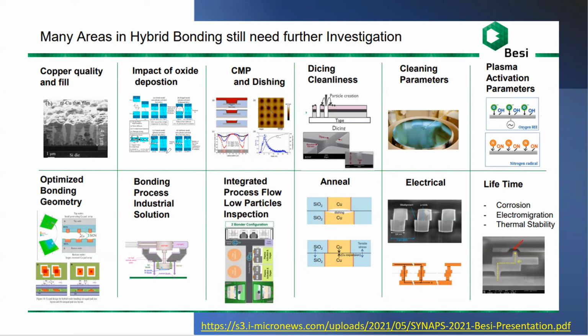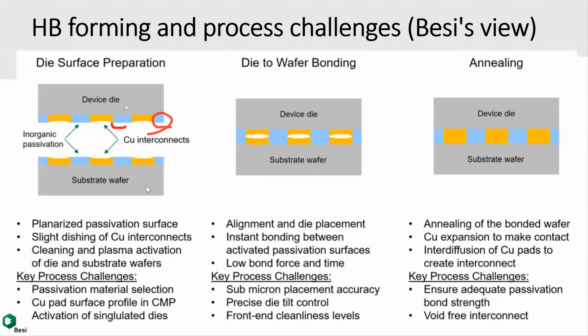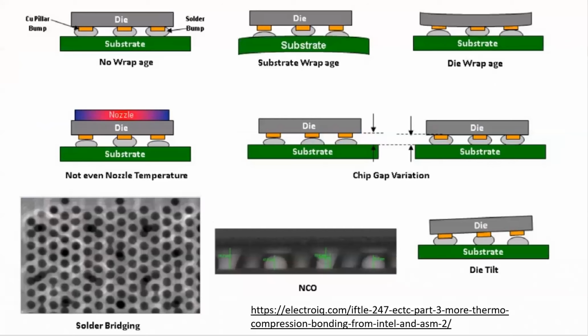And your oxide deposition also has the problem, right? You have to be super flat. This is a very easy cartoon, right? Very easy cartoon. And so they are all equal thickness. But in reality, they may not be. If you have different heights, then you're in trouble because you cannot form a bond, right? So that's a concern. If you don't form a bond, you have a void here, and copper can go in here. Then you have copper pad to copper pad contact, right? And bridging, just like here. Here is solder bridging, but imagine copper bridging could also happen because of that.